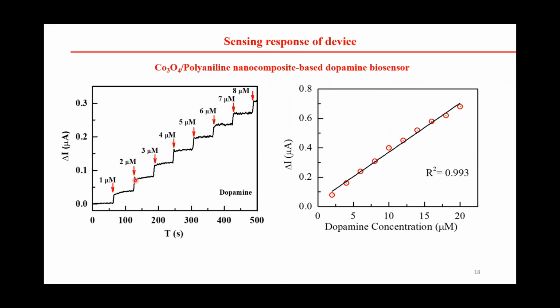In this case, we are using a glassy carbon electrode as the working electrode, and the cobalt oxide and polyaniline composite is deposited on the tip of the glassy carbon electrode. Here we can also see a linear response with concentration. This is a non-enzymatic method, because we are not using any kind of bioreceptor, so we can directly detect our desired analyte. In this case, we are detecting dopamine.